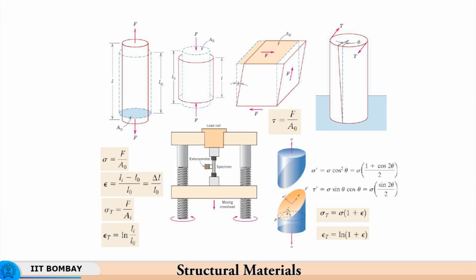Similarly, you have a shear stress that is generated within this plane, and the expression for that, on similar lines, is sigma sin theta cos theta, because the shear stress is F sin theta, and A divided by cos theta is the cross sectional area, and therefore, you have sigma sin theta cos theta equal to sigma sin 2 theta by 2. Now, the stress on this particular plane is a special case where theta is equal to 0. So, sigma dash will become equal to sigma, because cos of 0 is 1. But on any other plane you will have a different value as compared to the sigma on this plane.